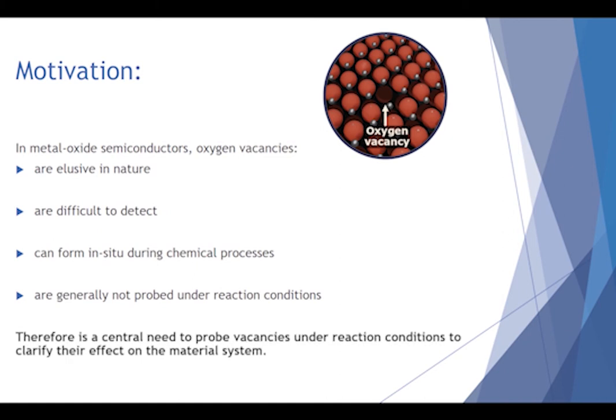the nature of vacancies themselves is very elusive. They're very difficult to detect, and very hard to understand how the concentration of defects that have been induced affects the overall performance of the film. In addition, these vacancies can form in situ during photocatalytic or different chemical processes, and therefore they can affect the way your reactions are happening whilst they're occurring. On top of that, vacancies are not generally probed under reactive conditions. They're very difficult to probe, and therefore often probed through scanning techniques under ultra-high vacuum, very low temperatures, or with single crystals. So, in conditions very far from ideal reactive conditions.